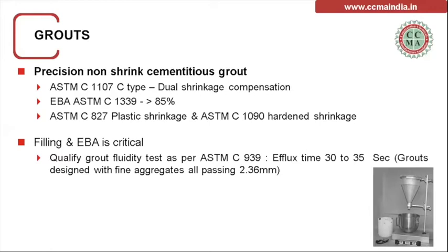Wherever we are designing a grout with aggregate less than 2.36 mm in size, it should pass the ASTM C939 fluidity test, where the flow time should be around 30 to 35 seconds. 1.7 liters of grout will be filled in the cone, and when they see the free flow from the cone, the material should be emptied in 30 to 35 seconds. This gives the right range of fluidity of the grout when we pour into congested reinforcement and all other places, even in column footing grouting where there is minimum space for the grout to flow. This is the best specification grout which can achieve all the intended results.